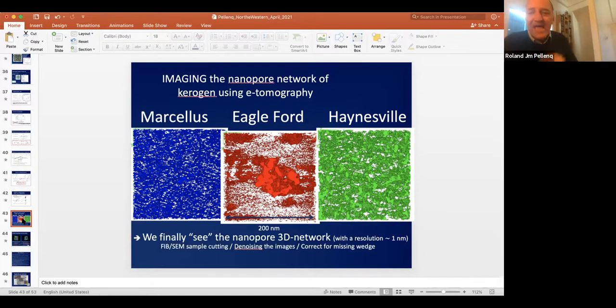And you understand why a mature kerogen that has very little oxygen, less than 1%, is hydrophobic, because the dipole of water has no place to interact, since there are no charges. It is van der Waals interaction, and the dispersion interaction of water with the carbon is way less than the CO2 interaction in this sense. But as soon as you put chemistry back, you populate the surface with oxygen groups, then you localize electrons, and then you make the water interact. So you transform this otherwise hydrophobic carbon into a hydrophilic carbon.